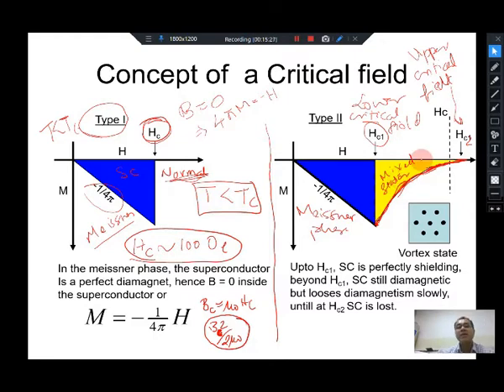It's a very interesting and characteristic state of type 2 materials, and these materials have a very large upper critical field. So from an application point of view, type 2 superconductors are very important. Superconductors, as you know, carry current with zero voltage. Suppose you make a wire and you want to operate it in a magnet. The magnet itself will generate a magnetic field, so you have a wire operating in a magnetic field environment. Now if its critical field is very low, just of the order of a few hundred Oersted, then immediately the superconductor will turn normal, and therefore you will not have the zero dissipation state. You cannot sustain current inside the material.